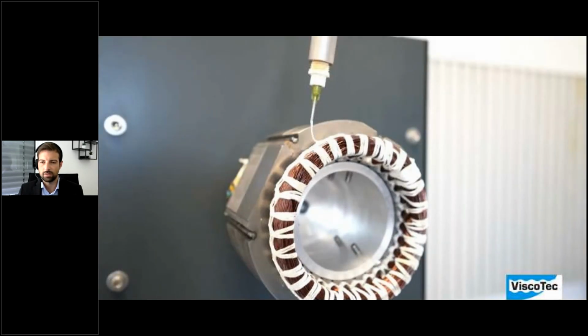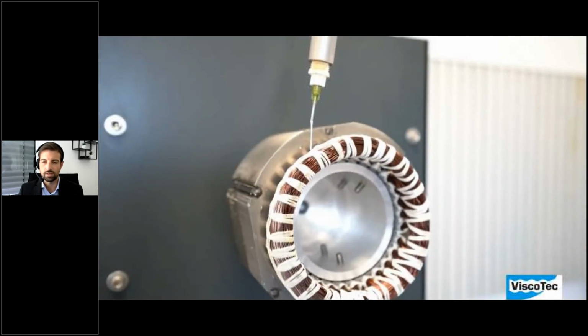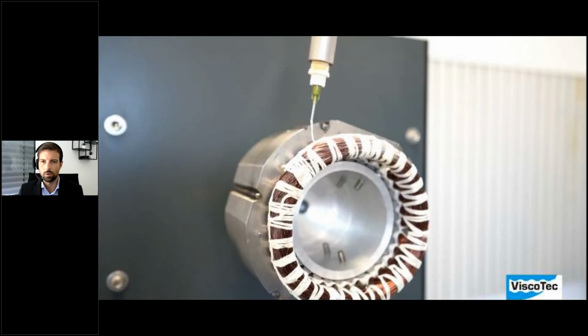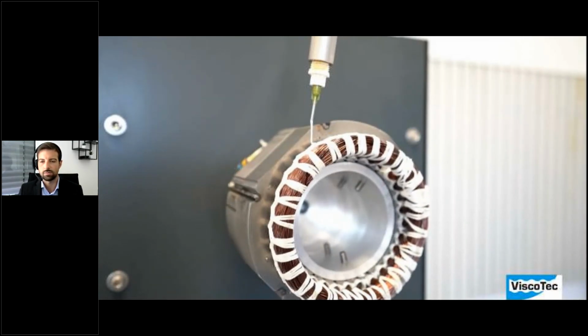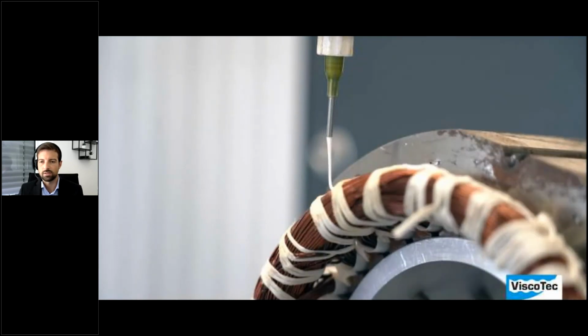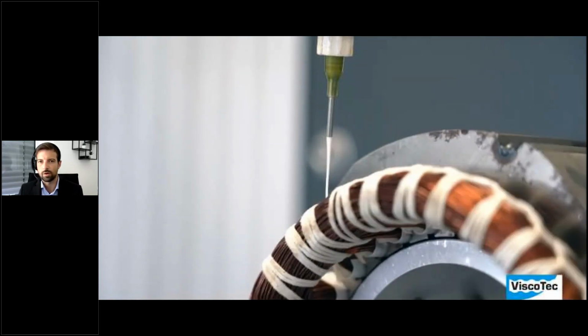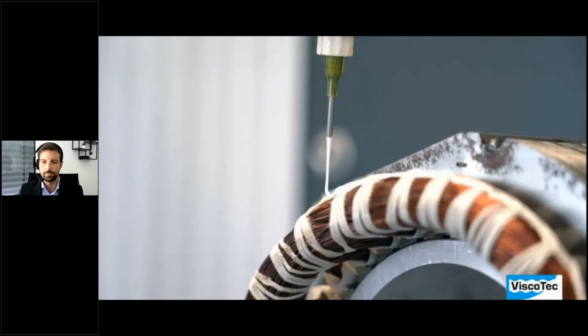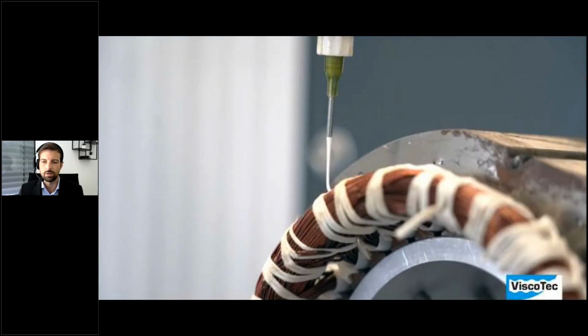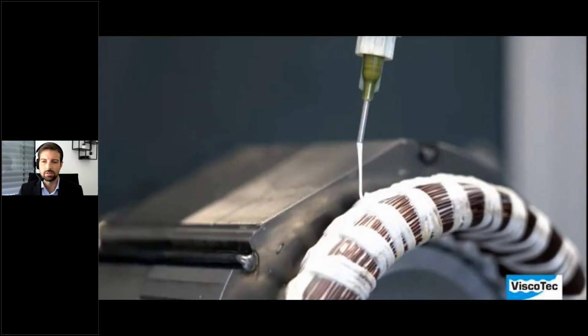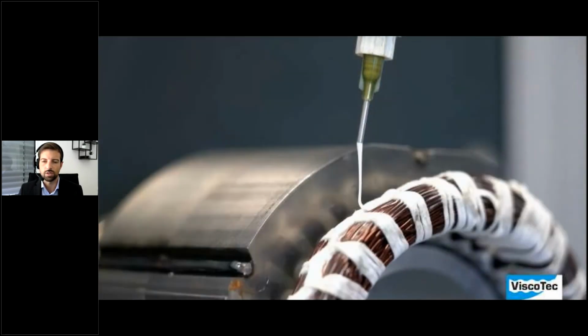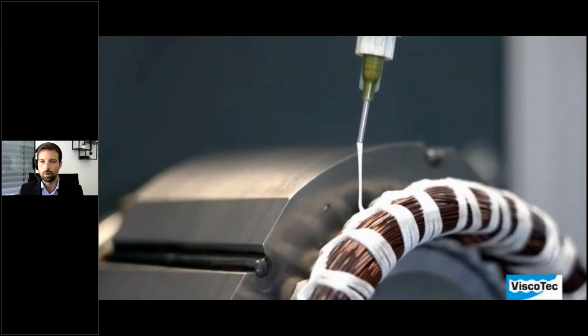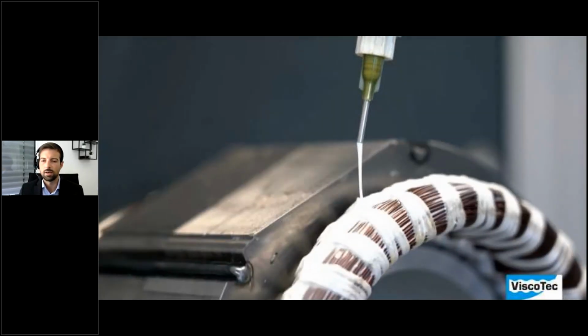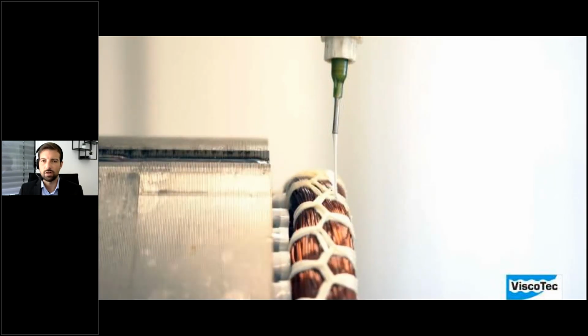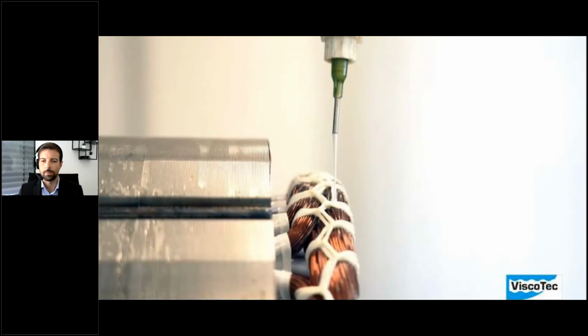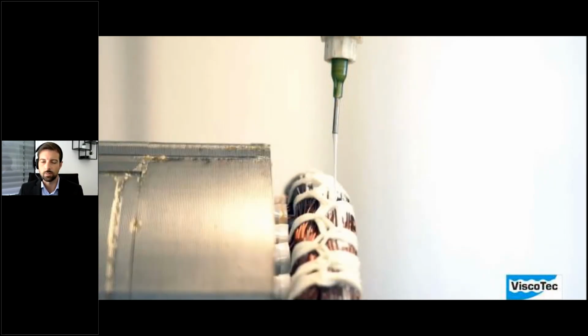The coils are rotating, and depending on the process, sometimes only one needle is needed for a dispensing process, but we can also implement several needles to increase the production rate. So this is a one-component dispensing material. The rotation is needed to get a better material distribution, and in case of one-component resins, we can achieve a faster curing time once the system or the coils are heated as well.